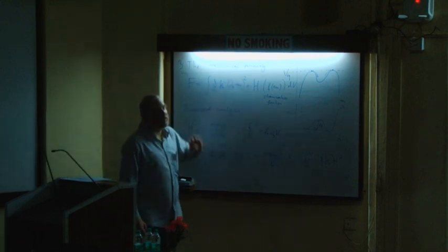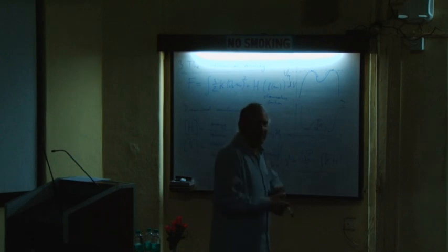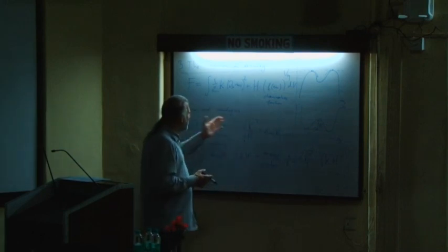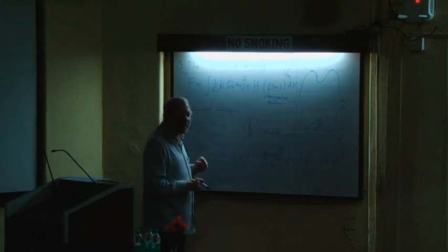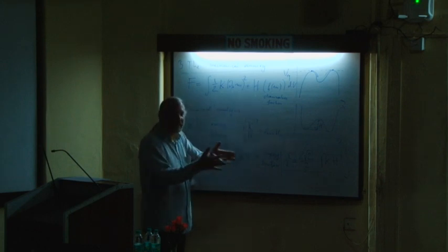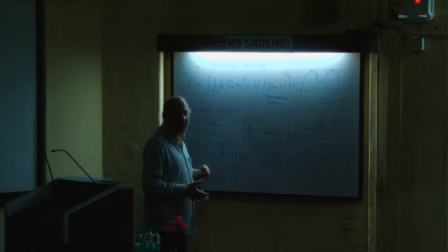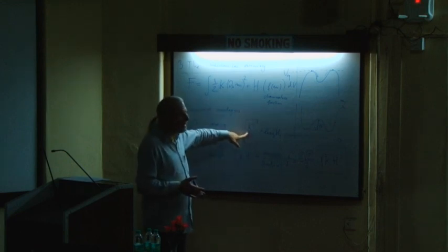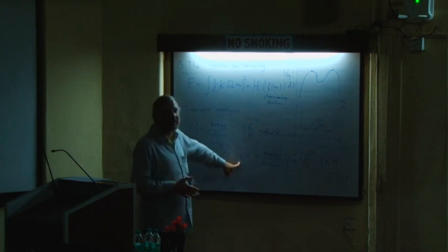So you see that these two constants fix a length scale and a surface energy scale, in some sense. So you can immediately guess that these scales have to show up somewhere. And indeed, in our calculation, we have seen that the interface thickness, meaning the width of this interfacial zone, is proportional to that. And we have found that the surface energy is proportional to that. Okay?